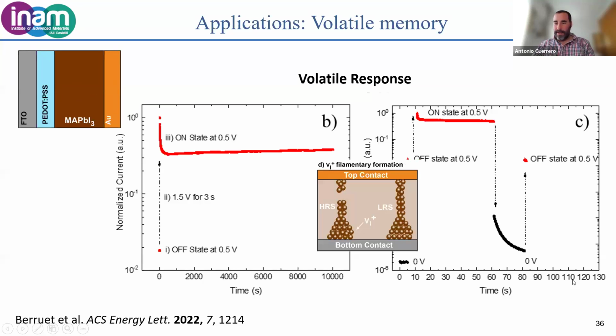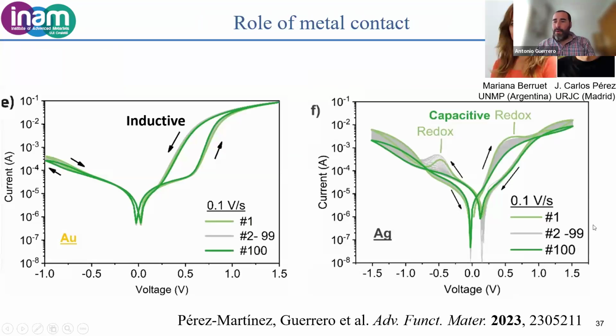So we recover very fast the highly resistive state when we are moving ions, just halide vacancies, inside the perovskite. Okay, but when we use metal, like silver, so in this case, this is what I just showed you with gold. If we use metal like silver, then we can see the formation of a redox peak. So this could be the oxidation of silver 0 to silver 1, so here would be to get silver iodide. And then if we go back to negative potential, we get the reverse reaction, we go from silver 1 to silver 0.